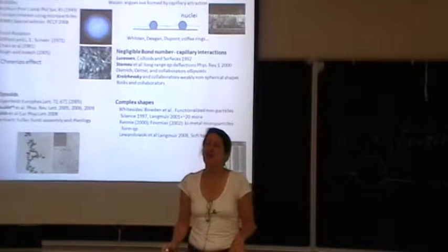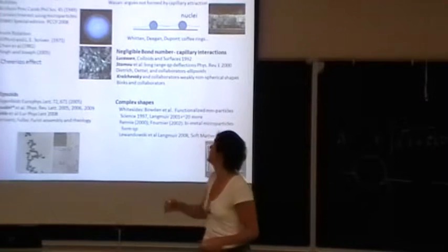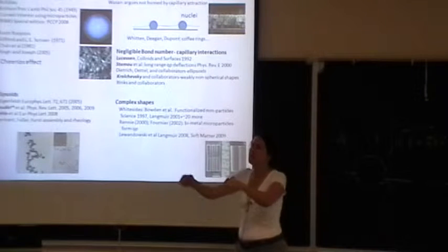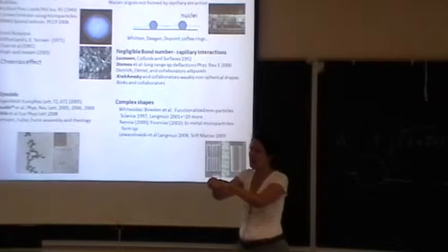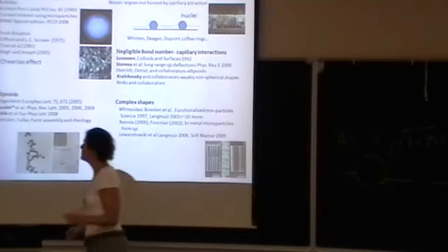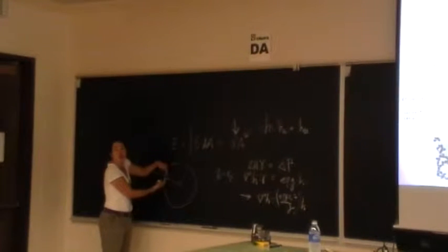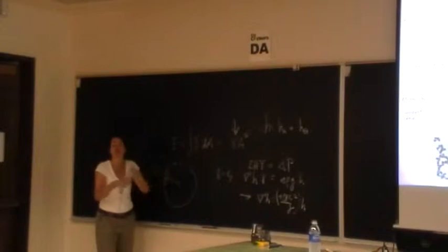Okay? This phenomenon harkened back to the colloidal crystal studies done by Kralchevsky and Nagayama in the 1990s, and they point to capillary interactions as being the cause of forming the nuclei. What Wasson says instead is that, this is the top view of the drop, the colloidal particles are being washed in the thin film, and the region between them remains sites of fast evaporation. So the particles are just being washed into the open section. These are not sliding along by capillary interactions. So this is an ongoing discussion, even the formation of the nuclei and the role of capillary interactions.